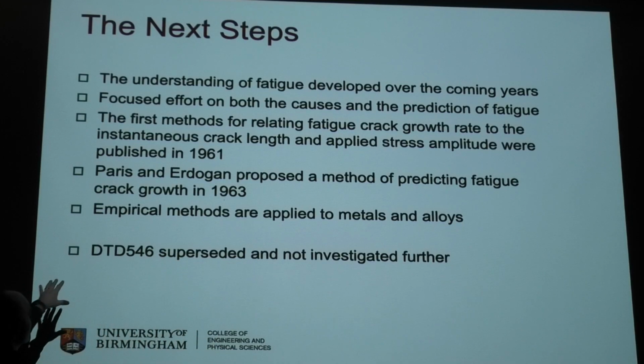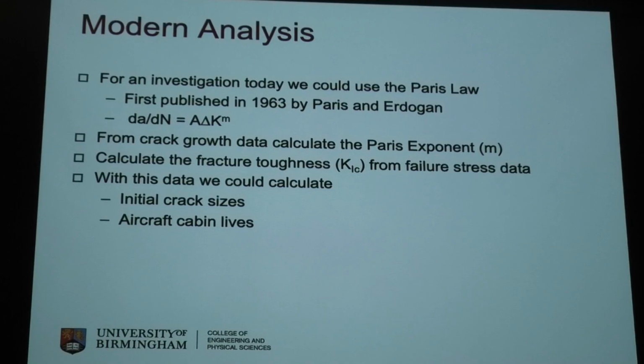And the alloy was no longer used. And so it got us to this place where we now understand fatigue a lot more. And we could use the Paris law to understand that, and this is where I'll whisk through, because this does more heavyweight maths. We can look at the number of cycles, or the crack growth rate per cycle, and the stress factor in there, and the fracture toughness, how long it needs to grow to. And we could calculate initial crack sizes, aircraft cabin lives, which is what we do today, as a first kind of approximation.